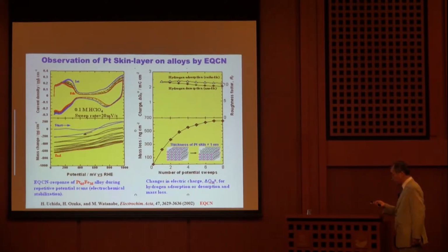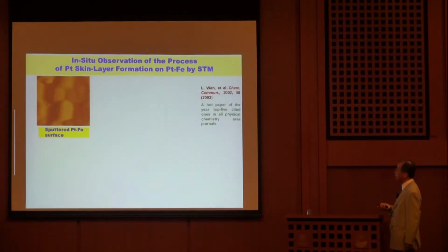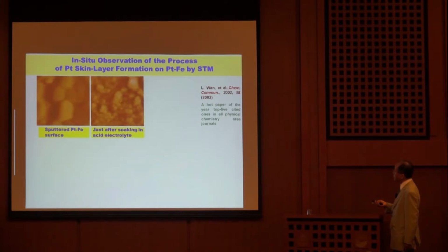So next stage, we use the STM system to observe the surface states. Here shows the sputtered electrode surface pictures observed using the STM on a platinum iron alloy surface. And after immersing the catalyst into the acid electrolyte, we observe the drastic surface morphology change just after the soaking.